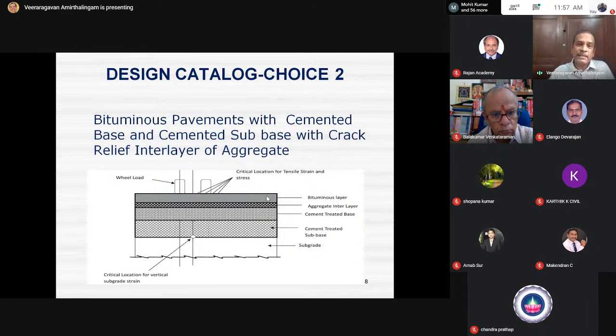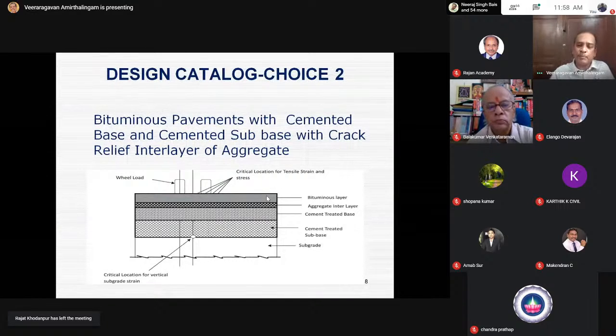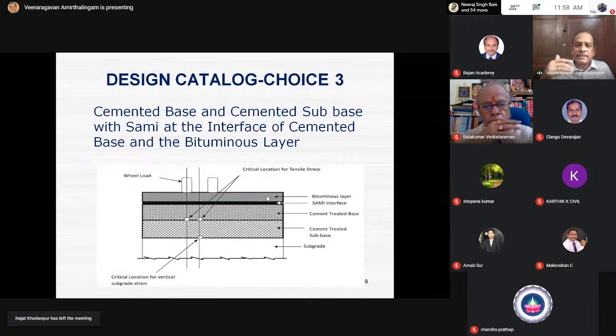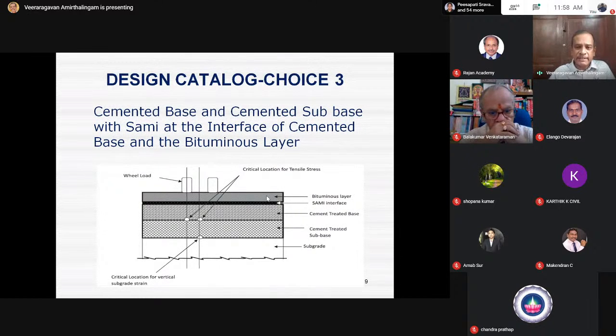You should consider what I said just now. The stresses coming at the bottom layers are much, much lower. So I don't require a higher percentage or dosage of cement. So when you have less than 2% cement, we found the cement-treated subbase is also equally permeable. So that question is addressed. Strength is better, with the result the thickness can be brought down. So in the case of structure 3, I have a subgrade. I have a cement-treated subbase. I have got a cement-treated base.